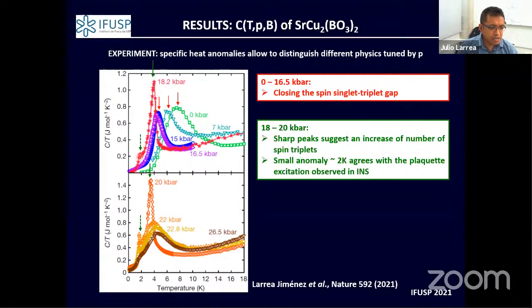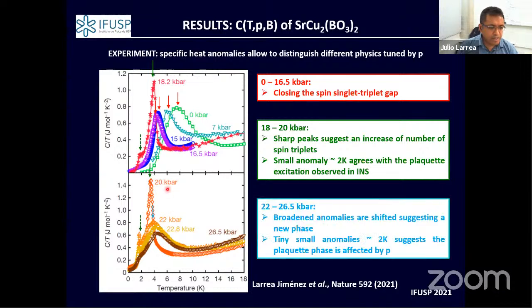This anomaly is related to another type of order or phase. What you can observe is that at 18 kilobar this small anomaly becomes stronger, at 20 kilobar. Afterward, as you increase the pressure more, the sharp peak starts to broaden again and move to higher temperature.